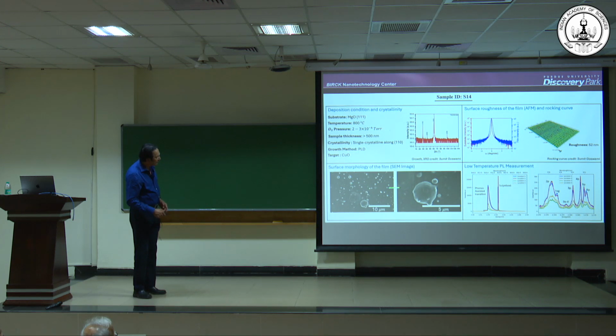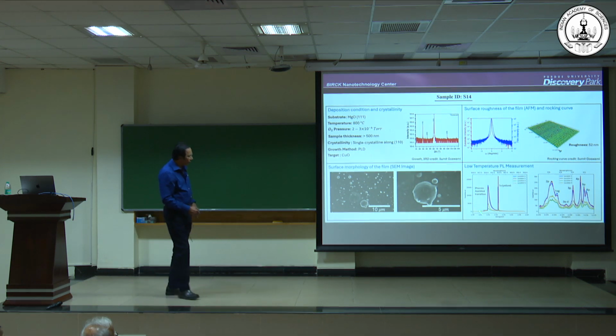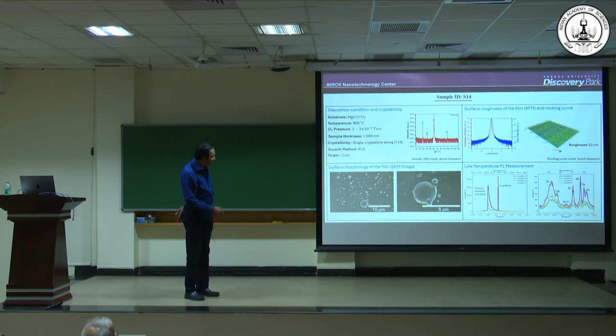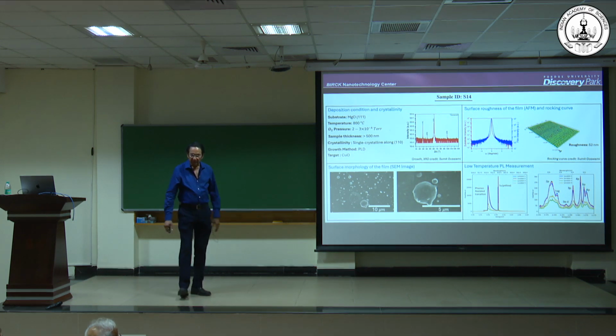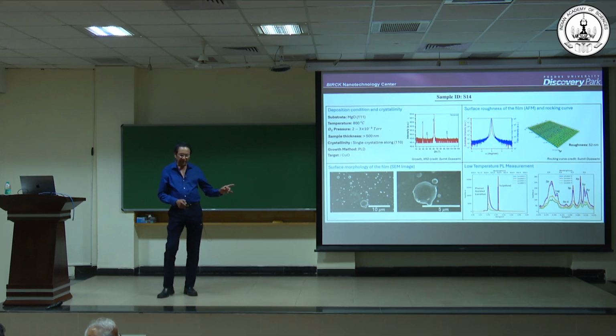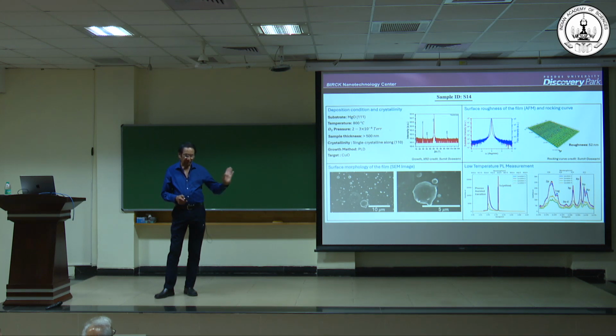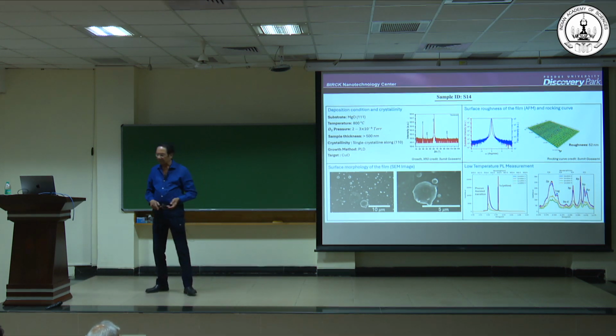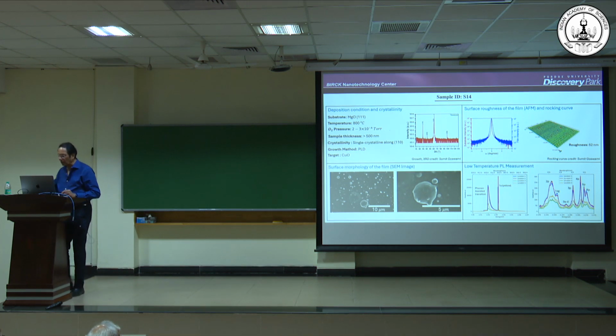When you go look at these now, these are PLD deposited films, and we can see the phonon assisted transition. We can see this very beautiful 1s exciton, and now you can see all the Rydberg excitons. Now you see 1, 2, 3, 4, 5, 6. So you can see them, right? And this is essentially done by photoluminescence. If we do a resonant absorption measurement, we can probably see many more of these excitons in this material. So this work is really ongoing, and it's extremely exciting.